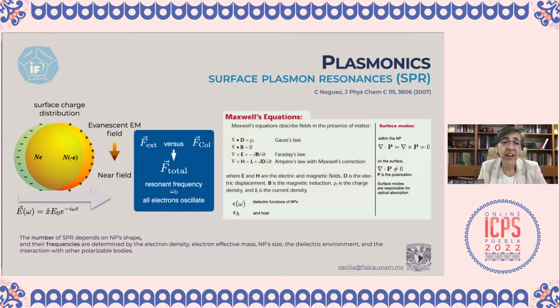Now, what we have to do to understand what is going on with this particle is solve the Maxwell equations in the presence of matter. And also we have to take into account this surface mode and this surface charge distribution, which is given in terms of the polarization field. One important thing that we have to consider is the dielectric response, or the dielectric function, of the nanoparticle, as well as the dielectric function of the host where the particle or the particles are in the system. So also we have to take into account that for these surface modes within the particle, this polarization field is equal to zero, the gradient and the rotational fields are equal to zero, and on the surface we have this surface charge distribution, and this is given by this equation.